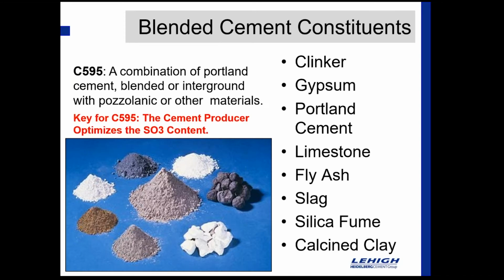So we're taking 2 things now from an inorganic perspective and blending those or intergrinding those. And why I think it's significant to do that from a cement producer perspective is because when the cement producer makes this blended cement, we're optimizing the SO3 content. And that's really important because of the SO3 that cement brings to that concrete mix. I think it helps us to understand we're talking no longer about constituents, we're talking about a system. So our concrete becomes an overall system where there's different components working together. And so the cement brings SO3 to that mix when all those things go into solution. And we're asking that SO3 to control a lot of different reactions. And so the cement producer is going to optimize that SO3 content on his end. And that is something I think that's going to be of benefit to controlling consistency of mix performance down the road.